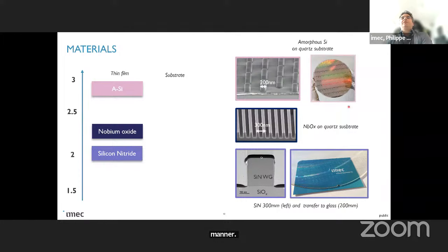We have been processing these different kinds of structure. So with the silicon nitride on glass substrates. So these are structures that are either directly processed on the glass or that are actually layer transferred onto a glass. We do the work for niobium oxide and amorphous silicon. Here you can see some examples of 200 millimeter wafers that have this flat optics type of structure.